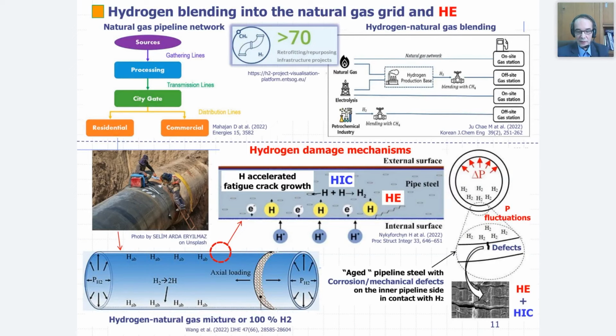But as you can see in down part of the slide, we have hydrogen damage mechanism. Down left, we can see a hydrogen natural gas mixture transportation, or 100% hydrogen transportation in existing gas pipeline. And we have three typical hydrogen damage mechanisms. The first one is hydrogen accelerated fatigue crack growth. The other one is hydrogen induced cracking. I will not talk a lot about this mechanism. And hydrogen embrittlement. It is very important, down right picture. It is very important to note the particular problem with aged pipelines with pre-existing corrosion mechanical defects due to long-term operation on the inner pipeline side in contact with hydrogen, which will represent the particular area very prone to both hydrogen embrittlement and hydrogen induced cracking, particularly when we have a typical pressure cycling of gas hydrogen mixture in our pipelines.